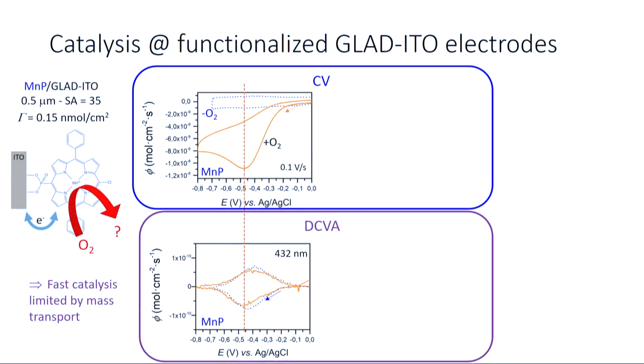And from the DCVA now, where you still follow, remember, the formation of the reduced form of the catalyst in the film, you can notice that you have a small delay here in the accumulation of the manganese 2, but still you accumulate very rapidly the reduced state of the catalyst, meaning that in fact you have a very fast catalyst that is limited by mass transport, and in your electrode you still accumulate a lot of the reduced form of the catalyst because it's not directly involved in the catalytic process.